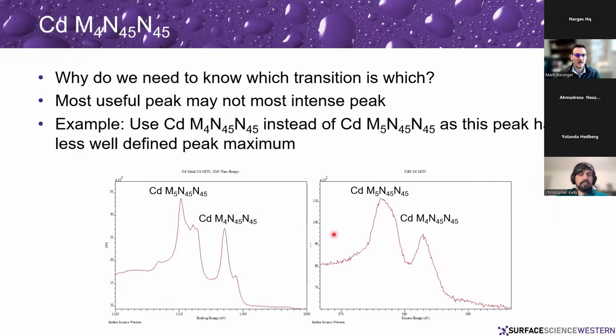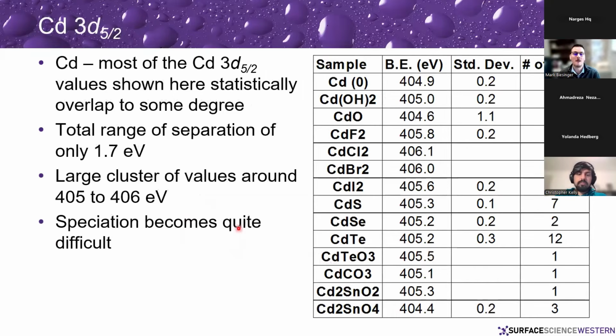And why do we want to do that? When you're looking at Auger structure, so this is a cadmium peak, you have to know which peak you're looking at. For example, we have the cadmium M5, N45, N45, and the cadmium M4, N45, N45. You have to know which peak you're using so that you can define which Auger peak that you're looking at. In this case, we actually use not the strongest peak, but the sharpest peak, which is the M4, N45, N45 peak, to calculate our Auger parameter.